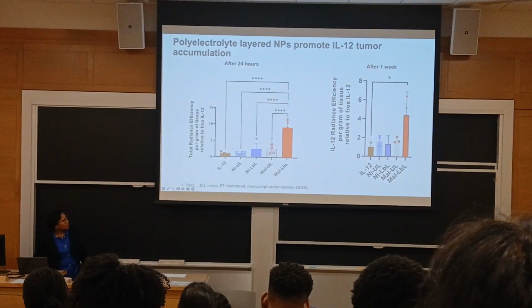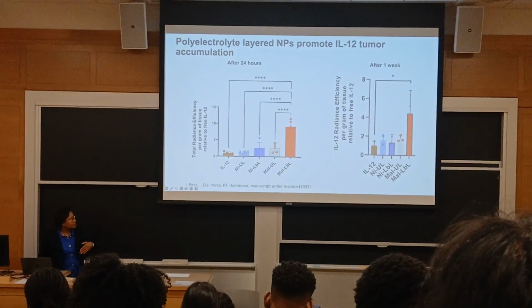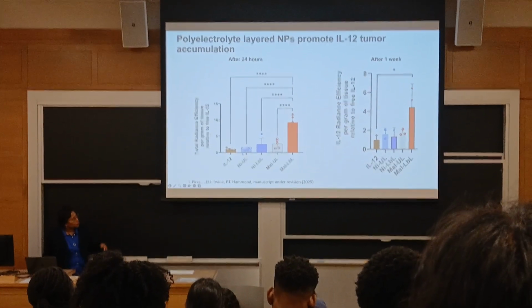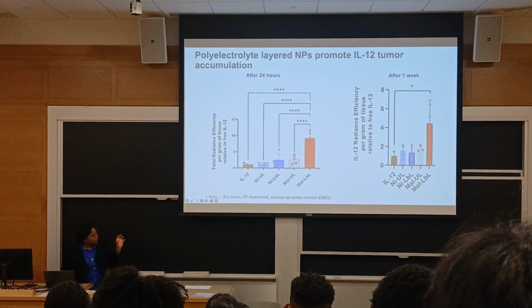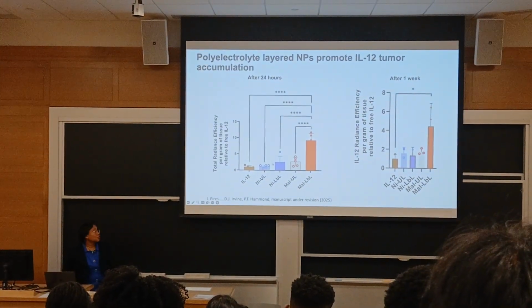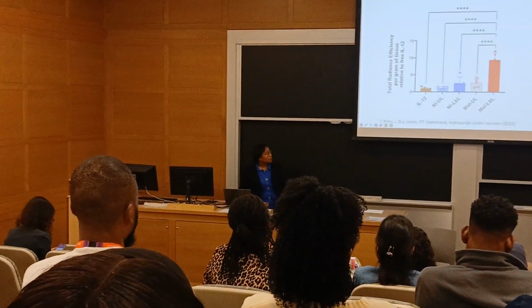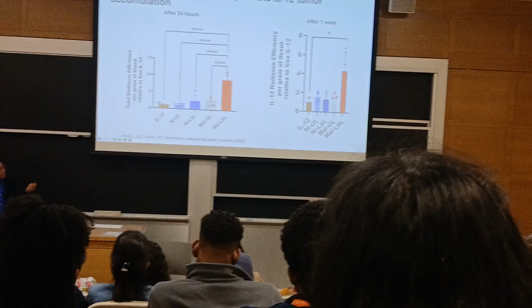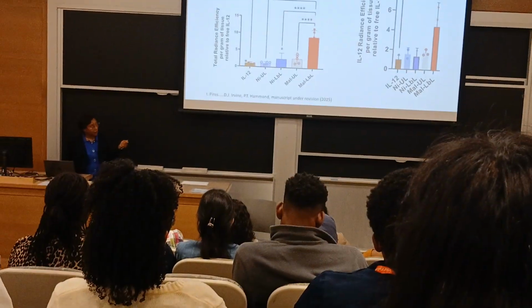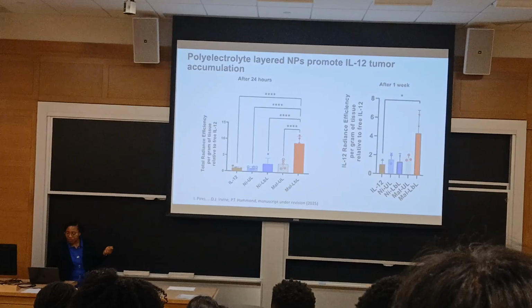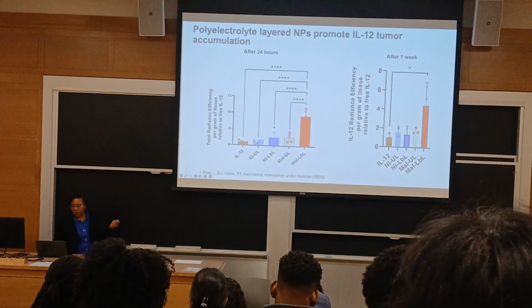Now, if we look at the IL-12 in the unlayered system, we're releasing it. After 24 hours, not much left. If we layer it, then it's sticking but still releasing. So after 24 hours, a little more. If we use the maleimide, which is the permanent linker, but we don't have the layers, it's not sticking. And so we have some happening here, but it's still not impressive.